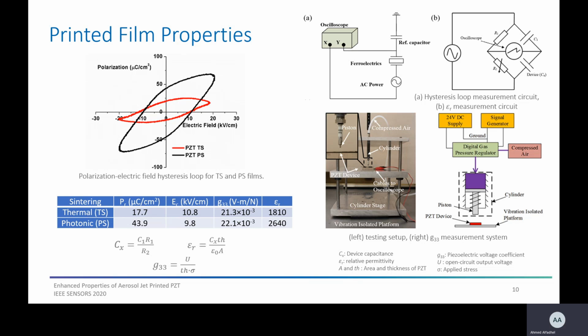Qualitative observations and quantitative measurements show enhanced piezoelectric properties and successful sintering of the photonically sintered PZT film when compared to the thermally sintered film. The enhanced properties can be attributed to the rapid photonic sintering process that prevents oxidation of the substrate, which adds an extra dielectric layer in the system. The piezoelectric voltage coefficient g33 was measured using a pneumatic cylinder compression system, where the output pressure has a direct correlation with the input signal voltage applied to the cylinder, which applies force to the PZT device, as illustrated in the testing setup.